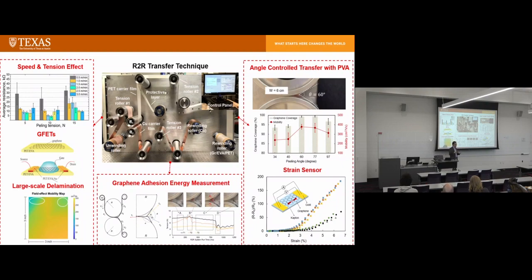Still, in the regular size, is still huge compared to what people do in graphene research. They only look at 13 micrometer size graphene. So this is still huge size graphene samples. We attach the graphene samples onto our carrier film, and then we can start to study the peeling characteristics of graphene. So we did a process study.